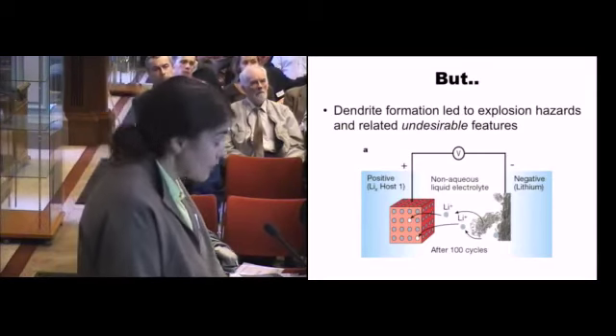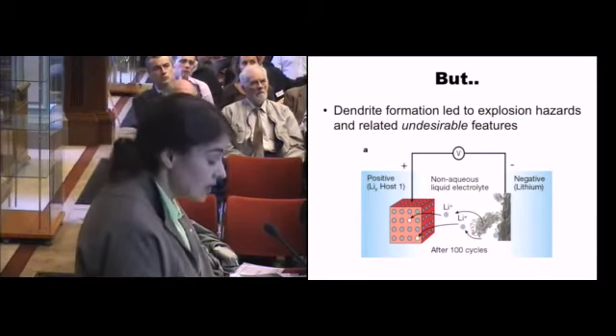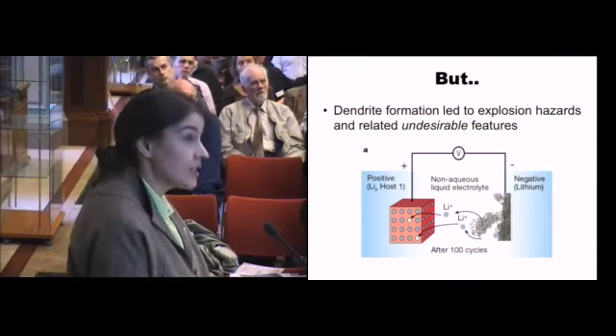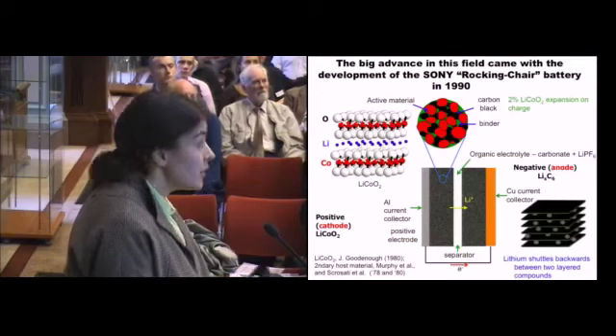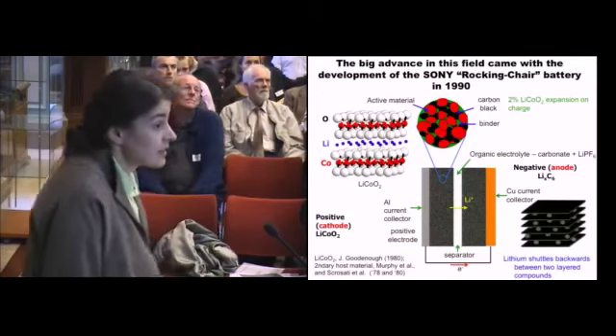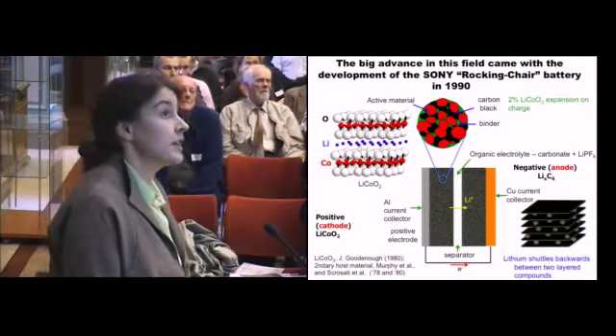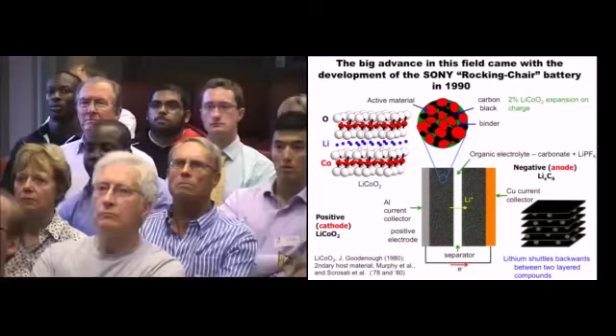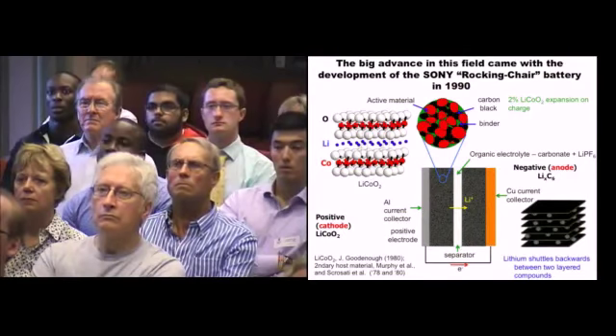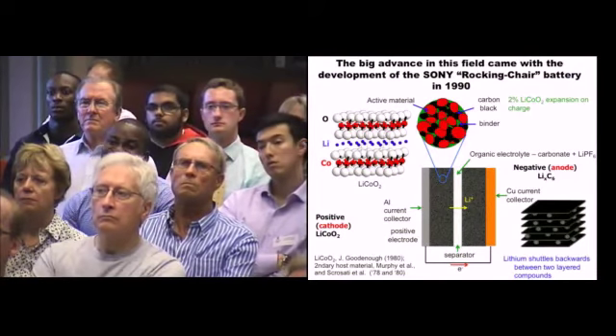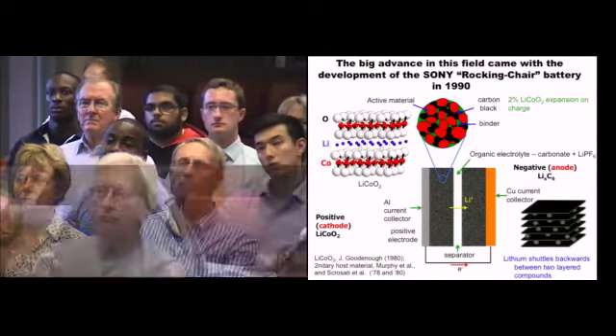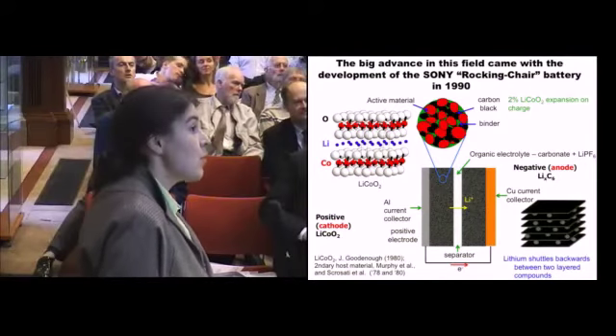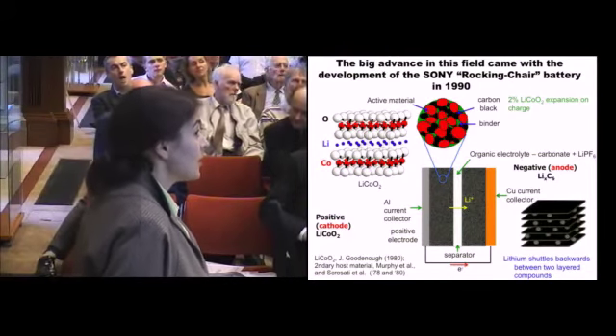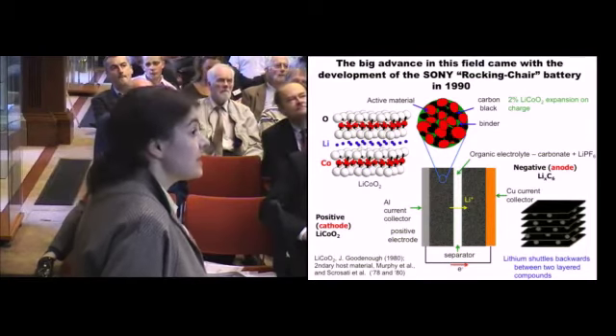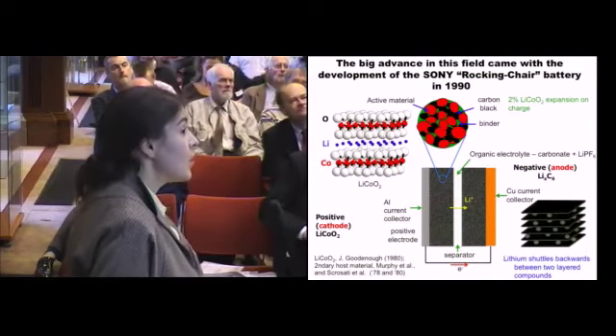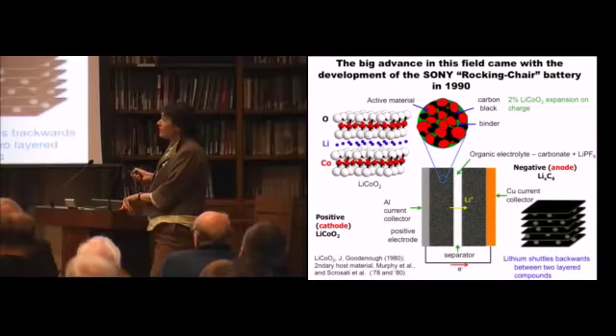And so that was pulled off in the late 1970s due to, obviously, some undesirable features. So it wasn't really till 15 years later that Sony put together the so-called rocking chair battery. And so they used the chemistry of John Goodenough, who was a chemist in the inorganic chemistry laboratory in Oxford in the 80s. So he'd been working on lithium cobalt oxide, very similar to lithium titanium sulfide, but now you've got layers of cobalt, layers of oxygen, and layers of lithium.